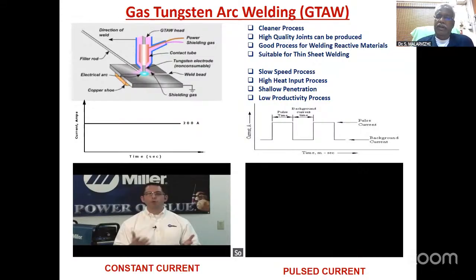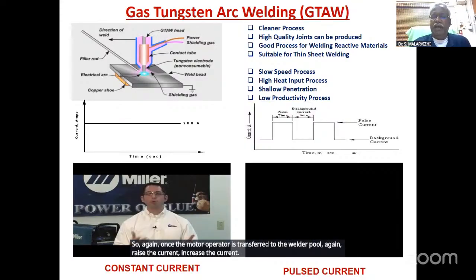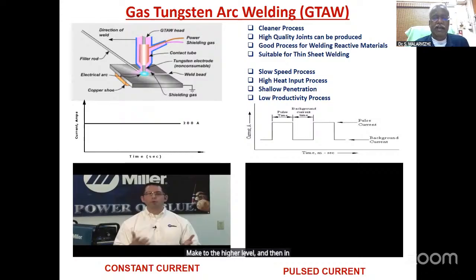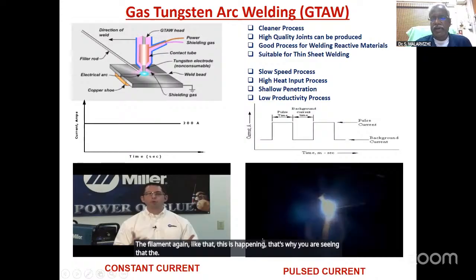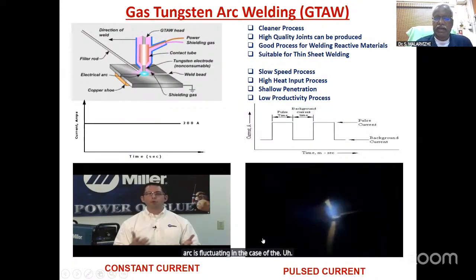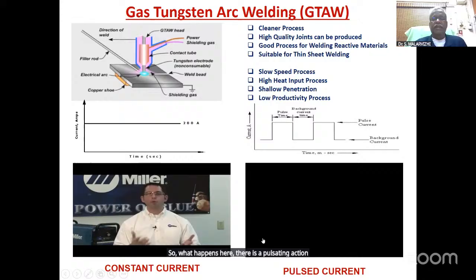Once the molten droplet is transferred to the weld pool, you raise the current again, bring it to the higher level, and then in the next cycle it melts the filler metal again. Like that, it is happening. That's why you see the arc fluctuating in the pulse current welding process. So there is a pulsating action between the pulses. The current varies from maximum, the peak current, to the base current. Because of the variation in the current, the heat input also fluctuates.